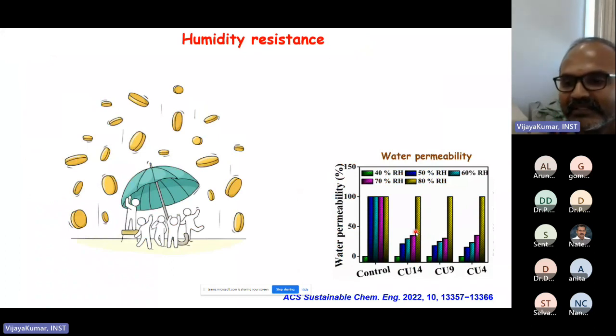And then the humidity resistance has been checked by keeping the coated material at different RH, and at different RH we are able to see that the liquefaction of urea is not happening in any of the materials except at 80% RH.